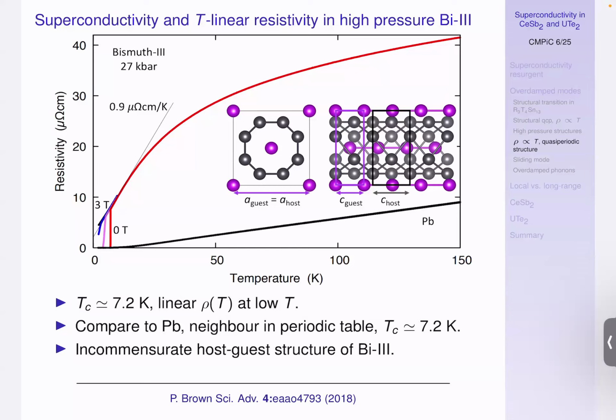And that was discovered in Edinburgh about 25 years ago by the High Pressure Institute there. These are all bismuth atoms, but you can think of it as two interpenetrating sublattices. The gray atoms form tubes. If you look down a cut of the material, you see a circle, and then perpendicular to the cut, you can see this extends into a tube. And the purple atoms form chains which line up inside the tubes.